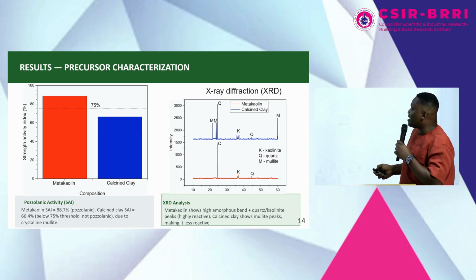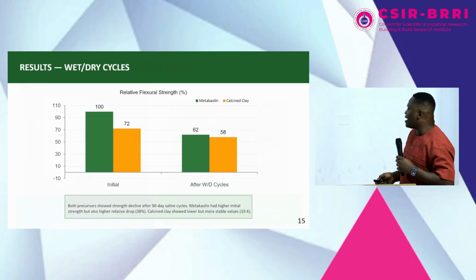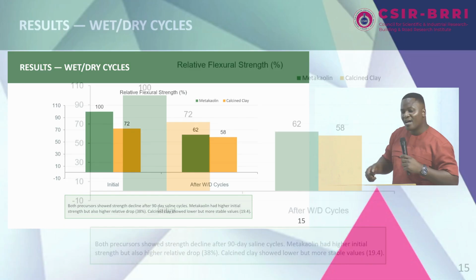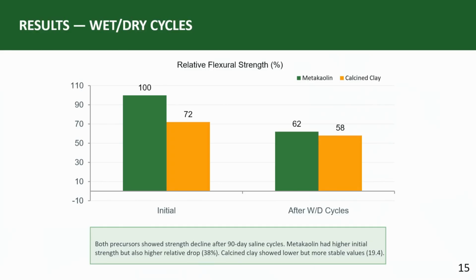But you realize that the mullite in this calcined clay becomes the main difference between that of the metakaolin and the calcined clay. As we go on, I will explain why it is so. All right. So these are results for the wet and dry cycle, i.e. soaking the material after they've been formed into the sodium chloride environment for a period of 90 days.